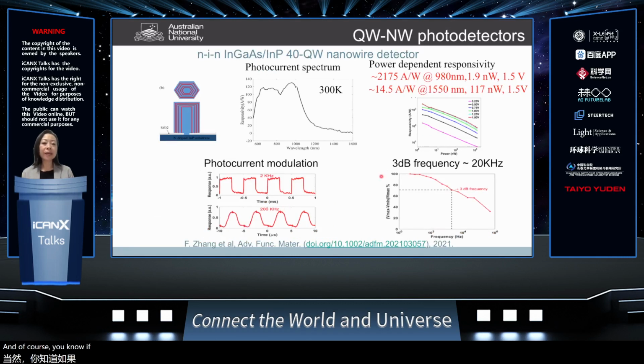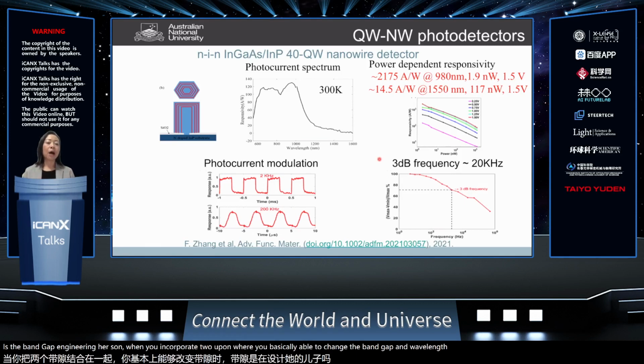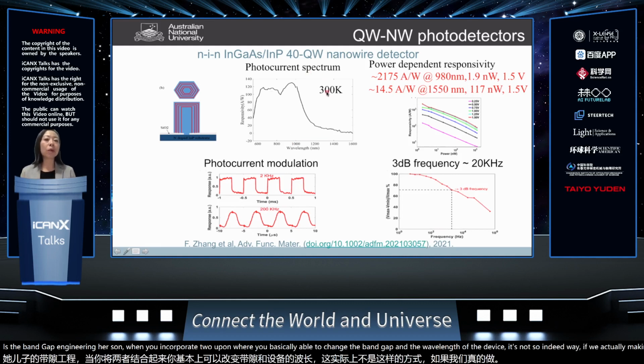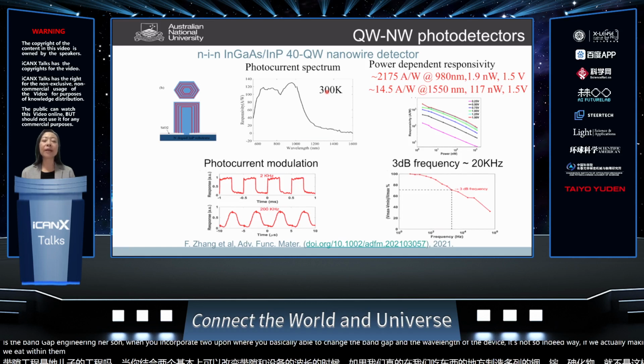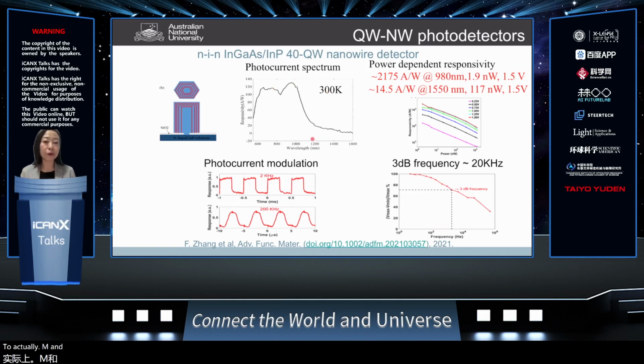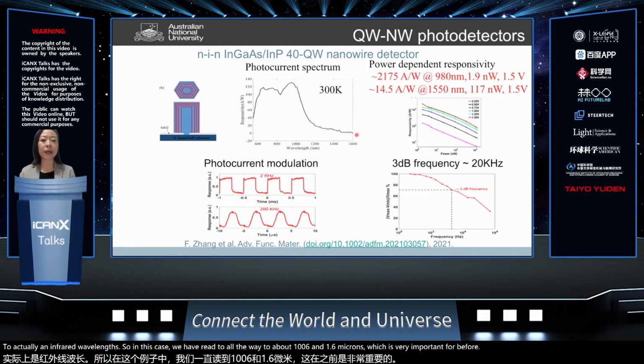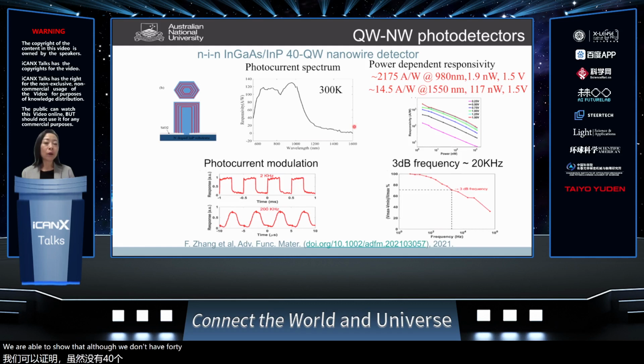And of course, if we can make quantum wells, as I mentioned earlier, another advantage is band gap engineering, because when you incorporate the quantum well, you're able to change the band gap and wavelengths of the devices. Indeed, if we make multiple indium gallium arsenide quantum wells with indium phosphide nanowires, we're able to extend the detection wavelengths from the indium phosphide wavelengths all the way to infrared wavelengths. In this case, we can go all the way to about 1.6 micron, which is very important for many applications. Although we only have 40 quantum wells inside these nanowires, we can achieve quite high responsivity at 1.55 micrometers, a very important wavelength for a lot of scientific research as well as applications.